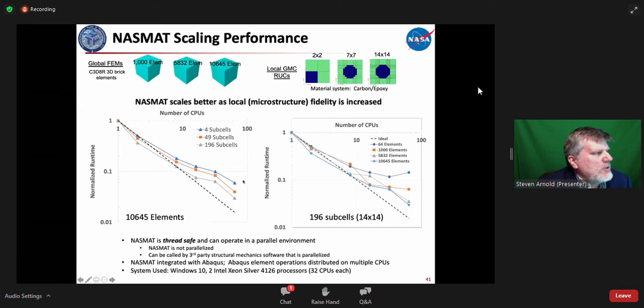And you can see you're not losing much at all by using sub-volume over the crack band in this case. We've also done a lot of scaling performance studies to try to understand how things are working, and what differences it might make between having really discretized models at the global level versus more discretized or higher fidelity RUCs. One of the interesting things that came out of that study was that the more complex the RUC is, actually the better we do in terms of matching ideal scaling. We think that's probably due to the fact that we're loading each CPU more uniformly. And once we get above a certain global discretization, it doesn't really cost us that much more to continue on and do additional elements. So that's the end of NASMAT.